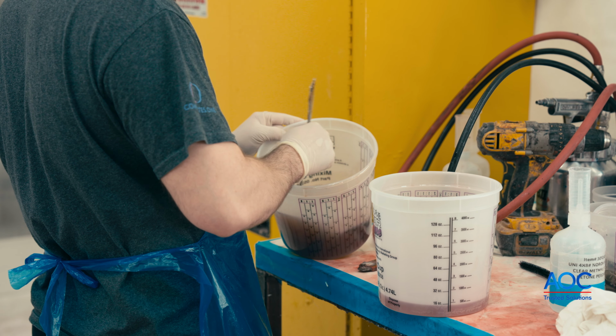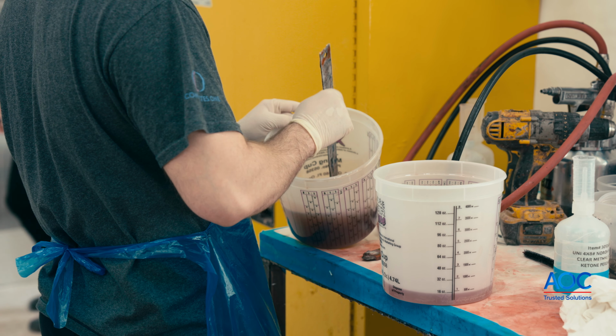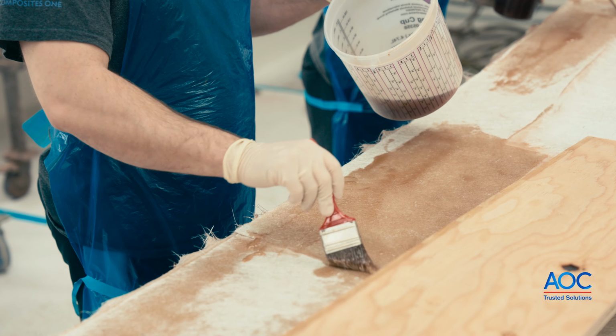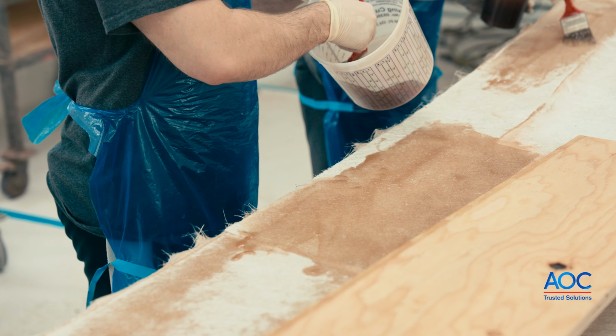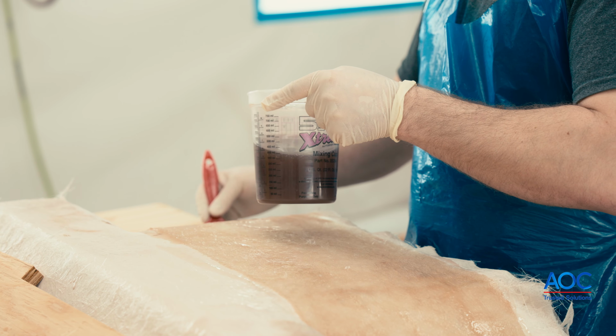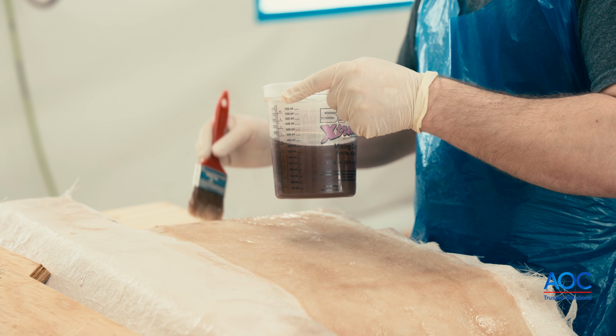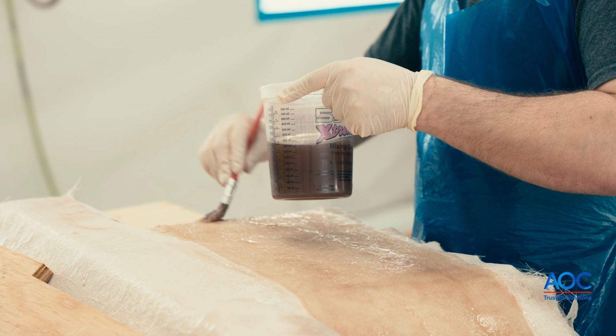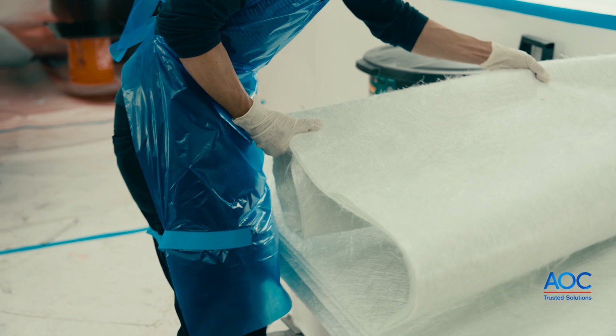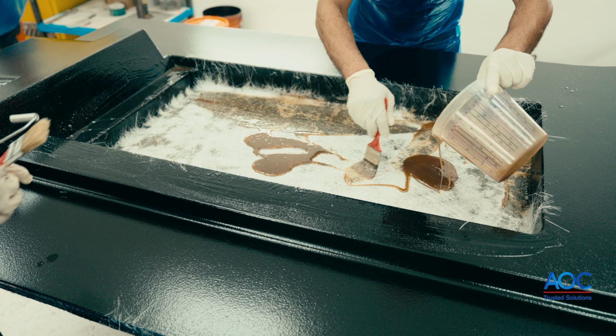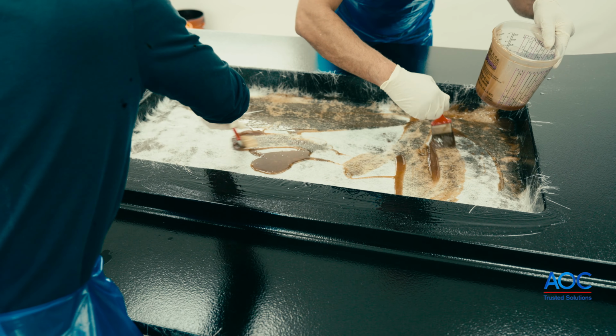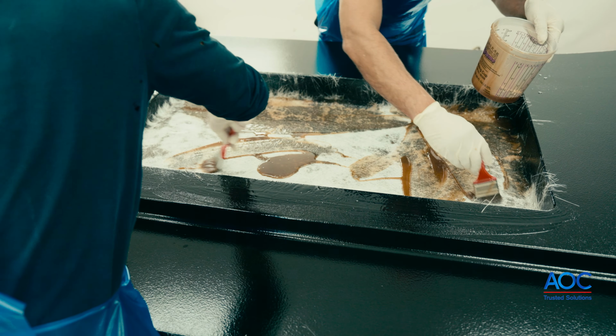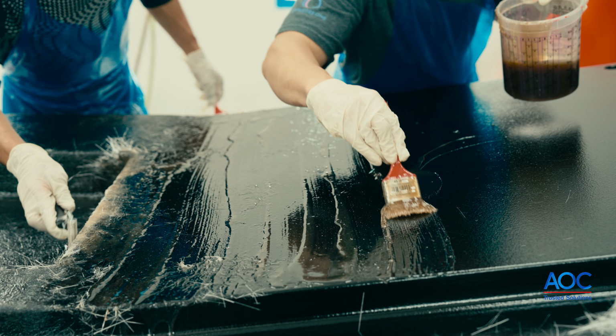Before adding the catalyst to your resin, be mindful of the activation time so the resin doesn't start to cure while it's being applied. Other factors that influence cure time include catalyst level, room temperature fluctuations, airflow, resin mass sensitivity, and humidity. Load the glass reinforcement onto the tool. Carefully position the glass according to your tool design and wet out the resin with a roller or brush. This will ensure that the resin is evenly distributed and remove trapped air bubbles and excess resin, strengthening the tool as it dries.